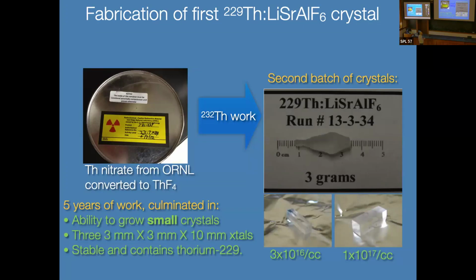The choices were driven by, it's really remarkable. The band gap is enormous, 10, maybe even 11 eV. We had materials tested at Los Alamos, and it was the lowest scintillator that they had ever measured. It's just a remarkable material. And that strontium site is really big, and so thorium can just slip in there really easily.